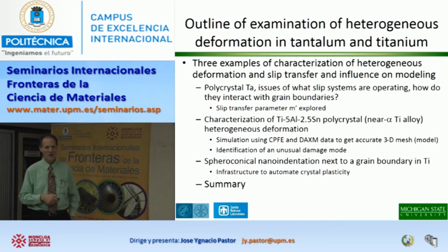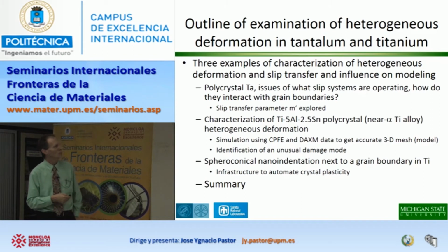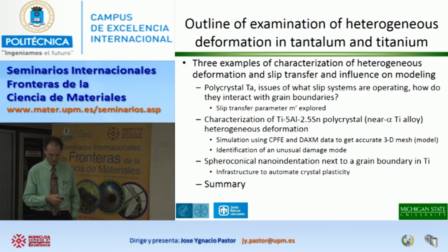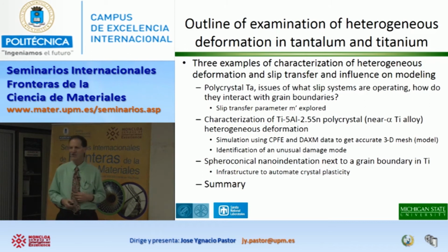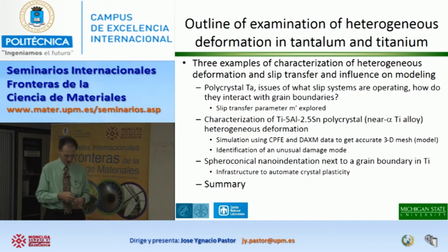So here's what I'll talk about the rest of my time. Describe a little bit in polycrystalline tantalum about heterogeneous deformation and whether or not we can predict which boundaries are more likely. Well, here's the difficulty. Heterogeneous deformation is a precursor to cracking. But the point I wanted to make is that if we can't predict the heterogeneous deformation correctly, then we surely can't predict where damage is going to happen correctly. So the real challenge with more ductile materials is, can we predict heterogeneous deformation accurately? So that's really where I'm shifting the focus.